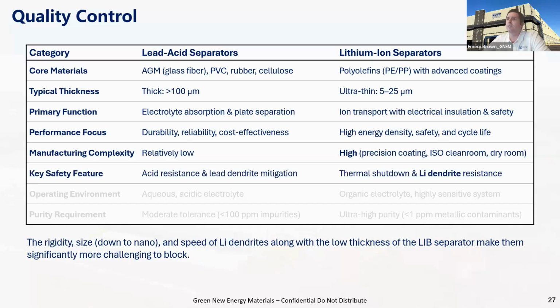Key safety features: lead acid needs to be acid resistant, with lead dendrite mitigation. For lithium-ion battery, it's all about controlling thermal shutdown, controlling and regulating thermal runaway, and of course lithium-ion dendrite resistance. Lithium-ion dendrite resistance is a lot more challenging, at least in my opinion. Why? We've never really solved it as an industry. We've come up with ways to extend cycle life. We've come up with ways to try to suppress them, but ultimately, we have not successfully eliminated the lithium dendrite problem. There are many reasons for that, but at a very high level, what we can say is these lithium dendrites are much more rigid. The size is down to the nano, so it allows them to creep through grain boundaries and through porosity. And the speed of lithium dendrites, along with the lower thickness of the lithium-ion battery separator, just make it much more difficult and challenging to block, if you will.